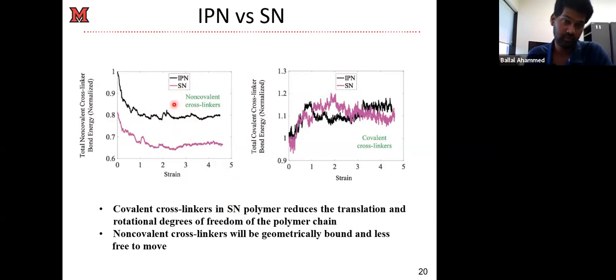The reason why more non-covalent bond formation happens in the IPN is this: consider two polymer chains. In the SN case, you have both types of crosslinkers. So one polymer chain has both covalent crosslinkers and non-covalent crosslinkers. As I mentioned previously, the covalent crosslinkers are very inert. They are very hard to break. So when one polymer chain gets crosslinked with other polymer chains in the case of SN, this covalent bond restricts the polymer, because when it gets covalently bonded with some other chains, it reduces the degrees of freedom for the polymer chains, like the rotational degrees of freedom and the translational degrees of freedom.